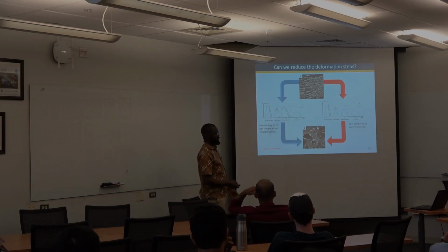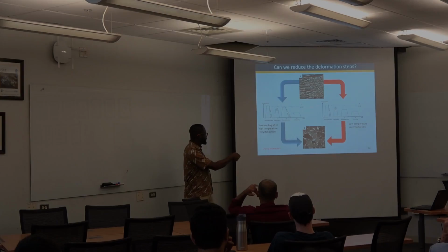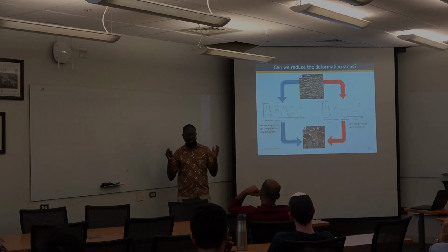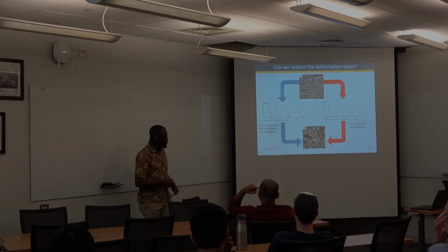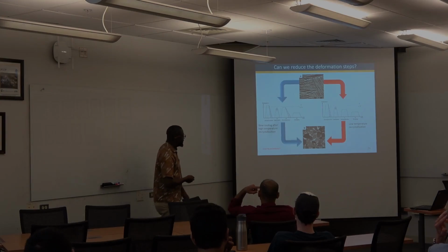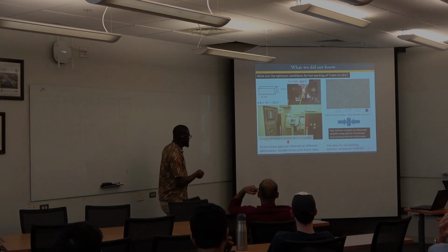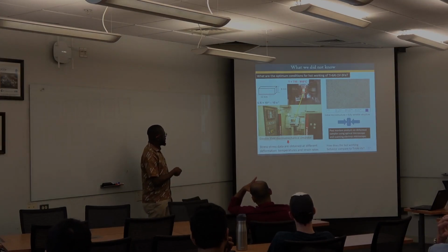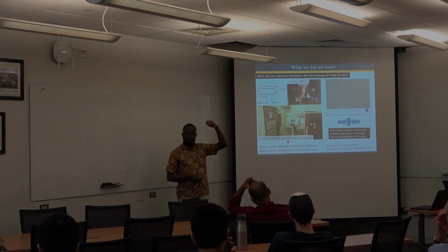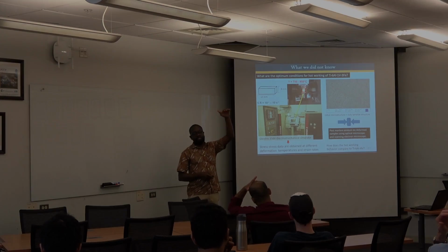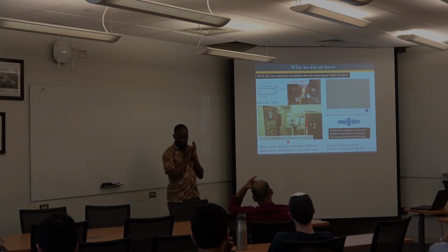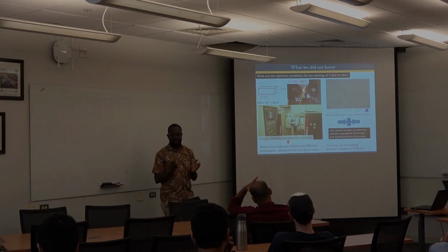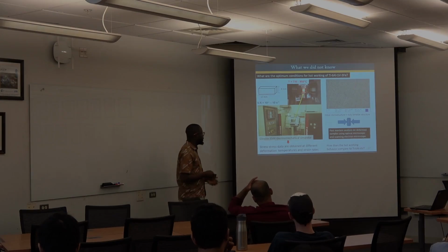So I thought, okay, I don't want to follow this particular process. Can I vary enough parameters under hot deformation conditions and arrive at something at least similar to this? And I'll show you. Like I said, in my lab we have this. I varied different strain rates and different temperatures. I didn't even do any beta homogenization at the beta phase at all. It was just deforming in the alpha-beta region because I believed that would save some of the cost of the analysis. And this was the initial microstructure, basically.